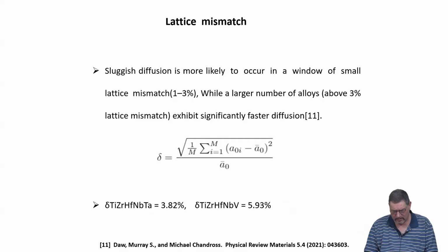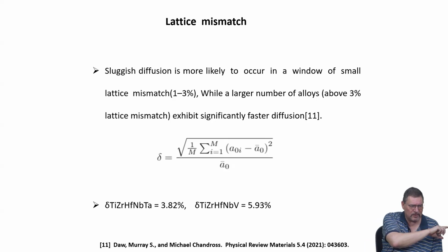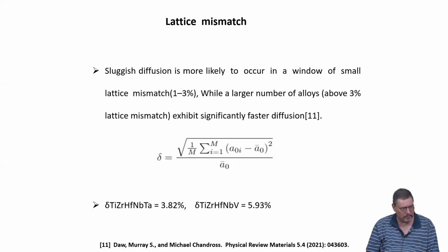But what also has been discussed in the literature is that sluggish diffusion is more likely to occur in a rather small window of given lattice mismatch between 1 and 3%. And if the lattice mismatch is larger, then it seems that faster, even accelerated diffusion can happen. And I think it's related to this potential energy landscape picture. When you have the larger lattice mismatch, then you have many of these sites which are energetically very unfavorable, and that can give rise overall in measuring accelerated diffusivity.